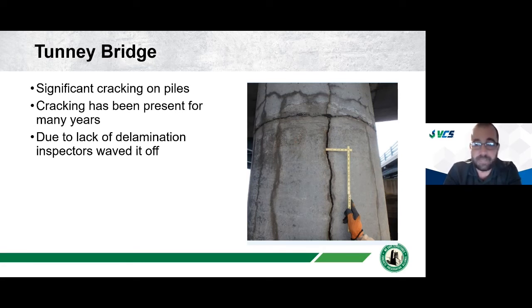And I was like, yes, I'm very concerned, because these cracks are in a marine environment, and in a marine environment, you're going to get water washing in and out of those cracks. So you may never actually build up enough iron oxide to cause the delamination. As that bar is rusting, it causes the crack. Now that rust buildup to cause the delamination is getting washed away by the water. So the crack may be all you're going to get. So in a marine environment, cracks are much, much more dangerous for that reason than in, say, a normal bridge deck exposure, say, in the Midwest.